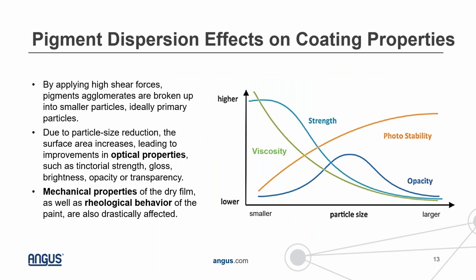And this is very important for a lot of different coating properties. Many properties, tied to either optical properties, mechanical properties, or even rheological behavior, are highly dependent on the particle size of your pigments in a formulation. Many of these properties can vary quite greatly, and most typically, they can be optimized if you optimize your dispersion of pigments.